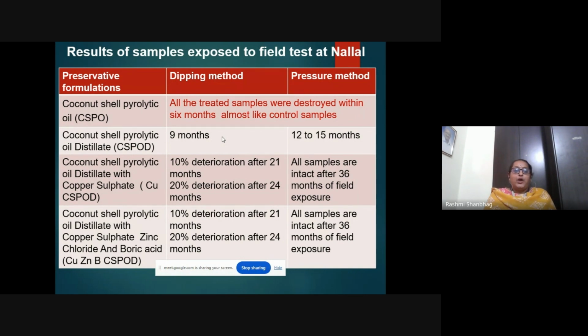Whereas the coconut shell pyrolytic distillate provided protection for a small amount of time. In case of dipping, it is 9 months, and in case of the pressure method, 12 to 15 months, the stakes treated with CSPOD remained intact. The stakes treated with the copper sulfate and CSPOD mixture showed, in the dipping method, 10% deterioration after 21 months and 20% deterioration after 24 months. In case of pressure treatment, even after 36 months of the field trial, the test samples remained intact. With zinc along with copper sulfate also, we found a similar result. Even after 36 months, the samples were intact.